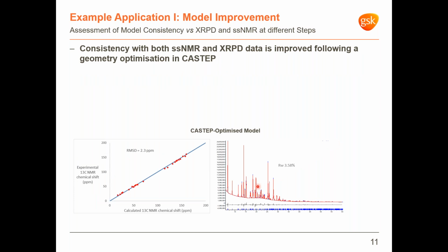Still, the CASTEP geometry optimisation allowed us in this case to improve the consistency of the model with solid-state NMR data, as highlighted by the reiteration of the solid-state assessment step here. And the final refinement confirms that the improved model is still well consistent with XRPD data, showing a slightly improved R factor.